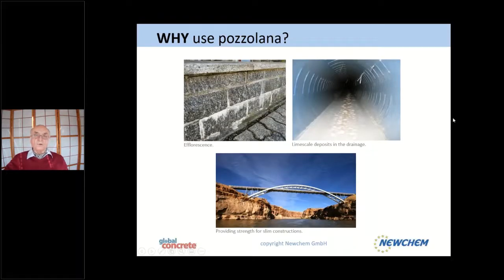Now, what is the problem, or why do we use it? The first thing is maybe here on the left side, you can see the efflorescence. That means that for the mortar which you use to stick your stones together, if you have some water pressure behind the wall, the water will seep through and dissolve your calcium hydroxide, which will come to the surface, react with the CO2 of the air, and you will get these deposits which are not very nice looking.